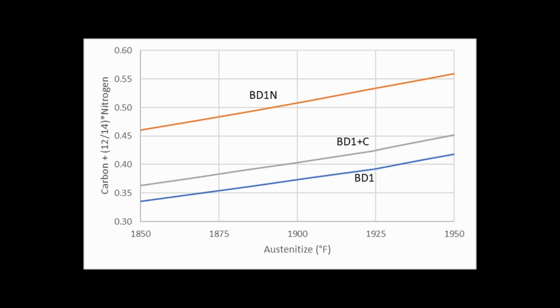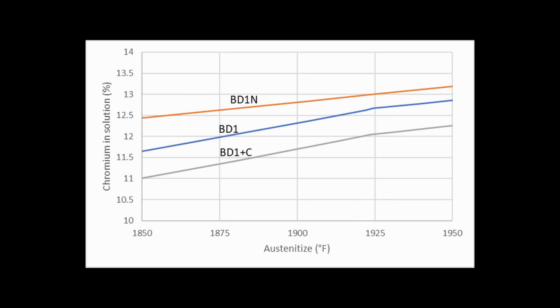And so not only do you get only a small bump in hardness, but you're also dropping your toughness by increasing the amount of carbide, and you're also getting less chromium in solution, so a decrease in corrosion resistance. Whereas adding the nitrogen, we actually see a small increase in corrosion resistance along with the increase in hardness. So we're improving the steel in multiple ways versus the carbon addition, which is a series of trade-offs.